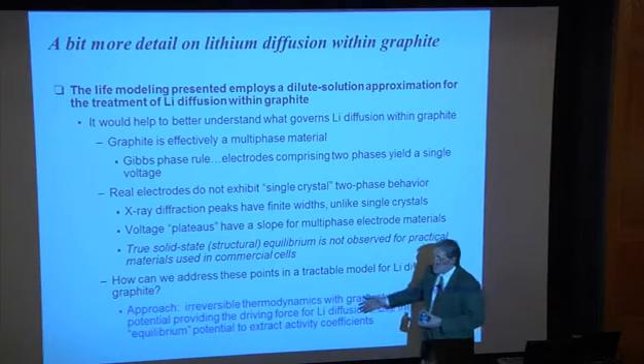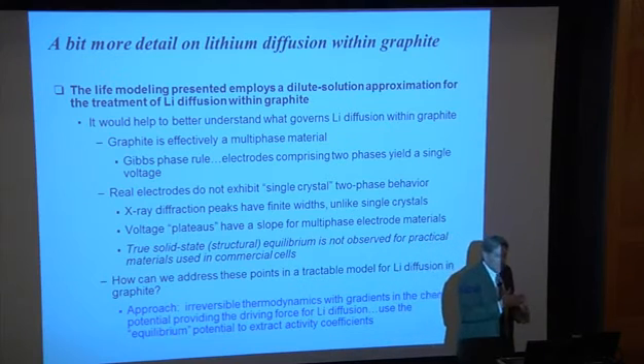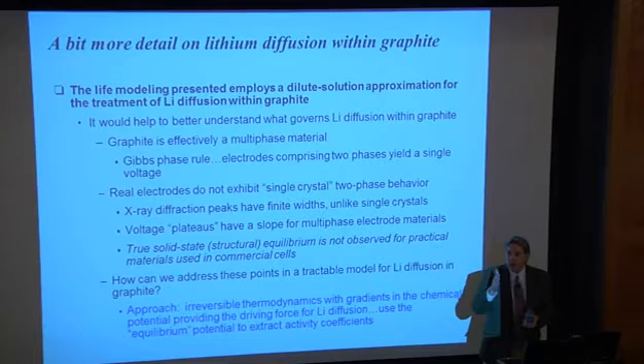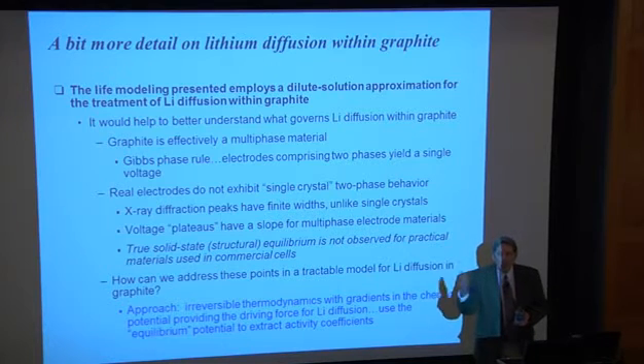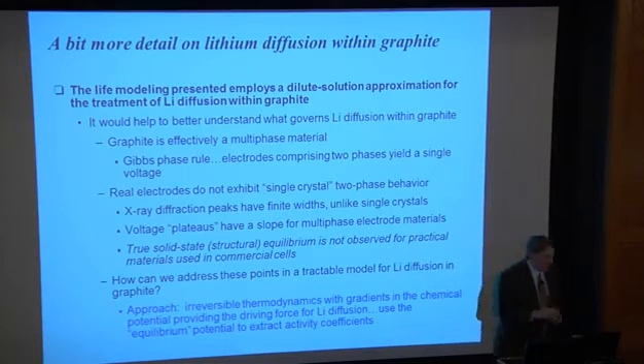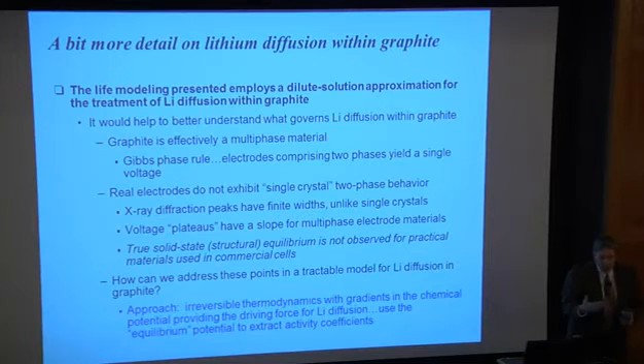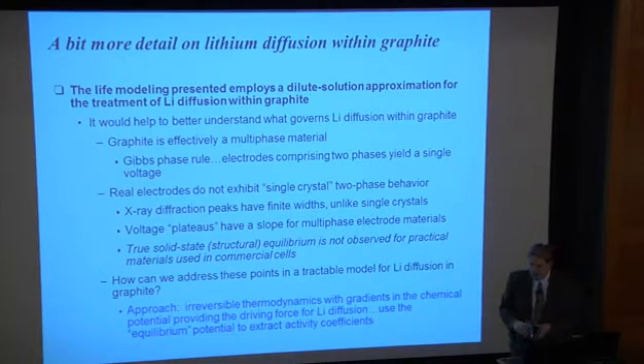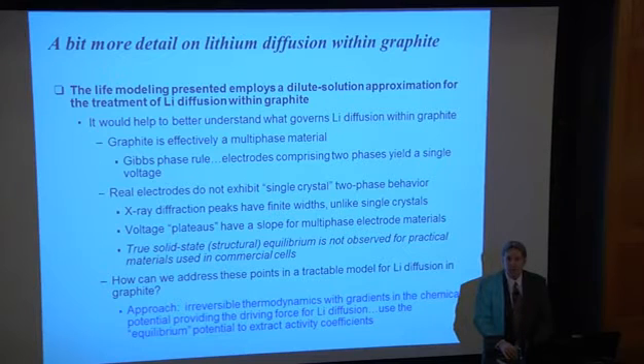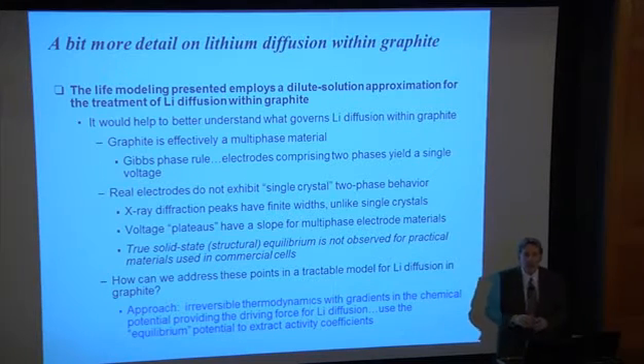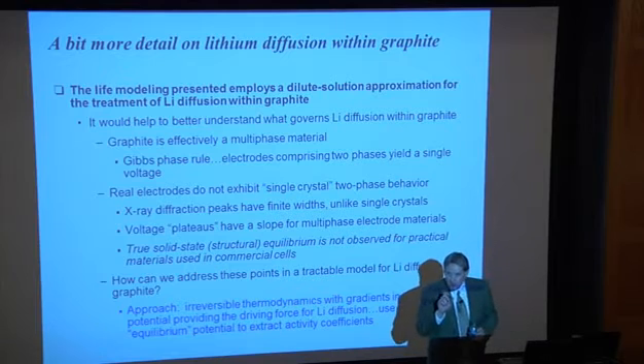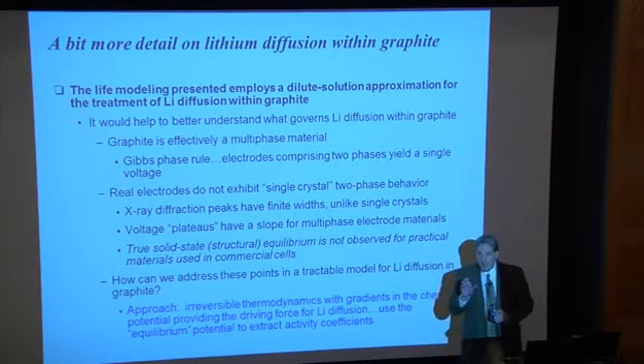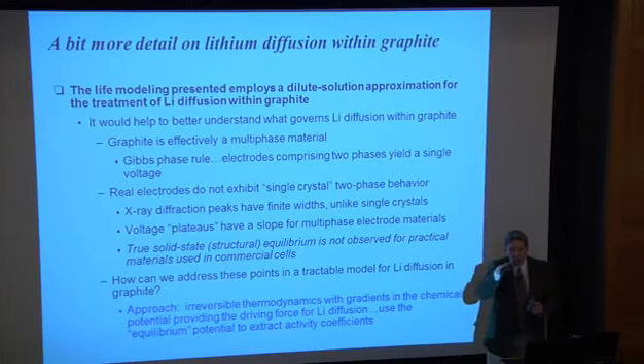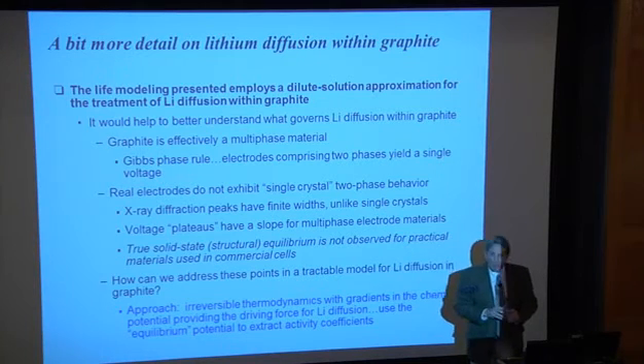But what we wanted to say was, look, graphite is actually, fundamentally, a multi-phase material. You have different stages. People who study carbon and solutes in carbon or lithiation of carbon refer to them as stages. And a metallurgist might refer to this as a multi-phase and grains in these systems. But at any rate, they have this multi-phase behavior. And the Gibbs phase rule will tell you that if you have 2 phases present and constant temperature, you're going to get a voltage plateau, which is indeed what you see with graphite. You have these voltage plateaus in graphitic materials.